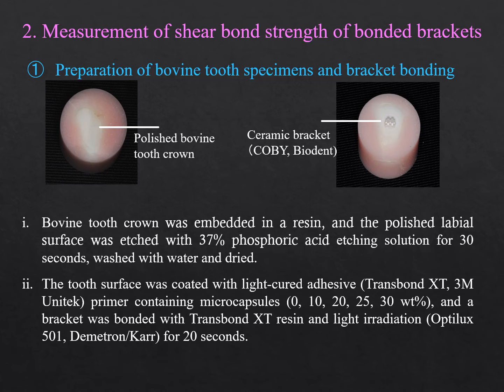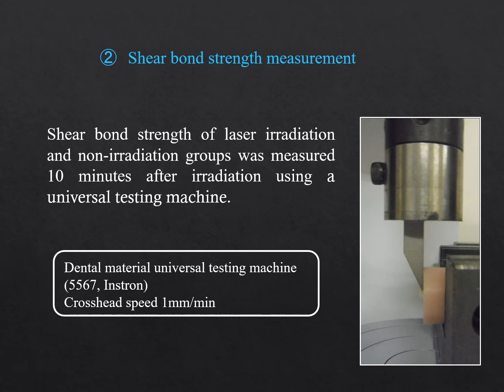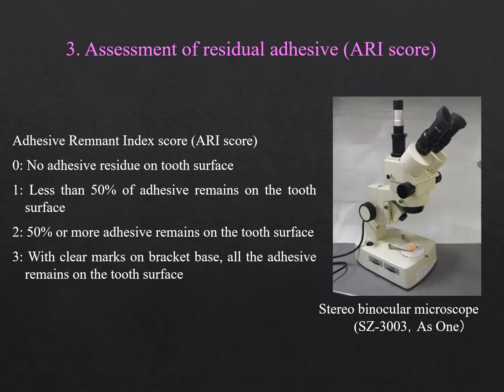The sample after bonding, the bracket was immersed in distilled water at 37 degrees for 24 hours. The shear bond strength of laser irradiation and non-irradiation groups was measured 10 minutes after irradiation using a universal testing machine. After measuring the shear bond strength, each sample was observed with a stereoscopic microscope at 15 times magnification to identify the fracture mode of the bond surface. The ARI score is determined 0 to 3, as shown in the slide.